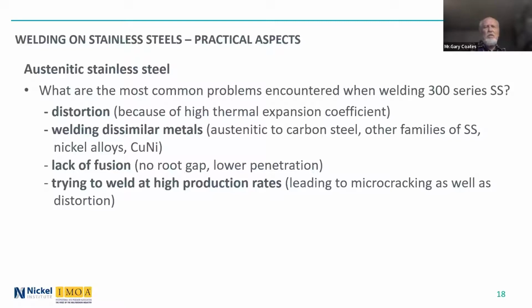Welding dissimilar metals is also difficult, again because of the difference in thermal expansion coefficient when you're trying to weld them together. It's not easy. There are complications when welding some of the copper nickel alloys to stainless. You have to use a butter pass or an intermediate pass. You can't weld the two directly together in some cases. Also, lack of fusion, no root gap, because the austenitic filler metals have a lower penetration rate than what you are used to with carbon steel.